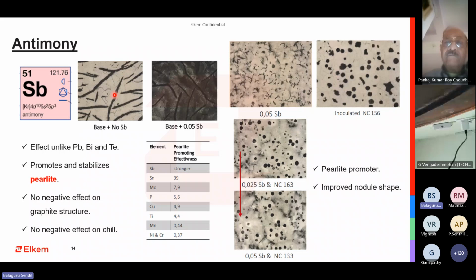So if you're trying to achieve a ferritic grade for your application, and you are seeing a problem of chunky graphite and you want to solve it with antimony, it can get solved, but it can also promote pearlite. It will definitely promote pearlite, and then you need to play with your knockout to do correction for this, which requires more process control to have good ferritic grade castings made with antimony. It is better to control this with inoculation. So that is what I would like to say with respect to antimony.